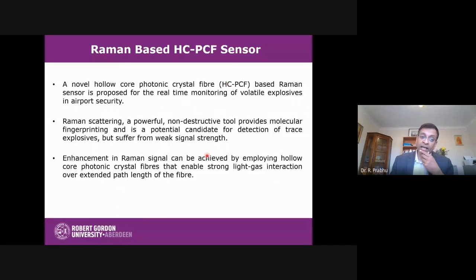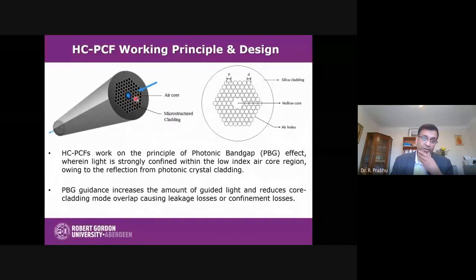So here, the idea is to use the molecular fingerprints of these vapors using Raman spectroscopy, and use photonic crystal fibers, which can increase the electric field pattern or distribution inside the hollow core fiber. As I said earlier, one of the recent developments in optical fibers is hollow core PCF, where the central part is hollow and the light can go through this hollow part. So the laser can come through this hollow part and we can tune the amplitude distribution or intensity of this